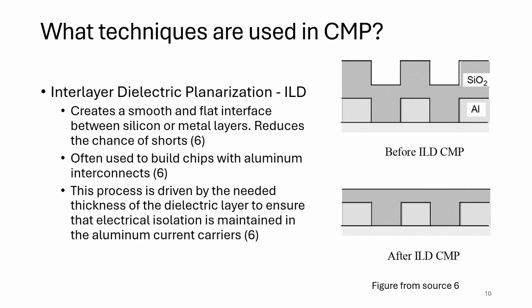For interlayer dielectric CMP, we are flattening an oxide or low-K dielectric to hand a level surface over to the next patterning layer. Here, abrasives, often colloidal silica, dominate removal. Chemistry is typically milder, where the mechanical components do more of the flattening work. The challenge here is avoiding erosion in dense areas while achieving global planarity.